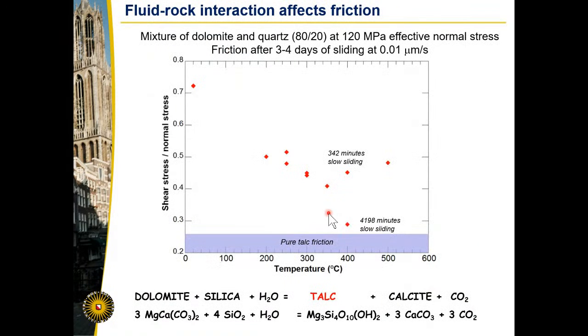Now I'm going to jump straight to some results. So in this apparatus, I performed experiments on mixtures of dolomite and quartz. So these are basically simulated fault gouges at 120 MPa effective normal stress at different temperatures up to 500 degrees. And the sliding velocity was something like 10 nanometers per second.